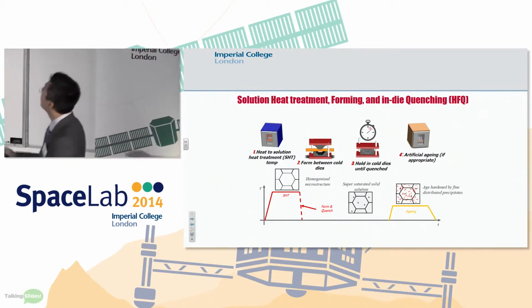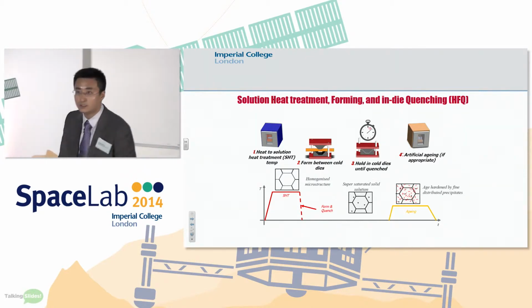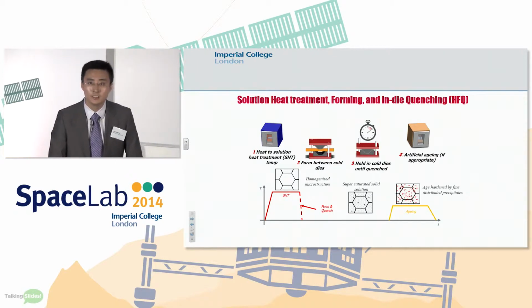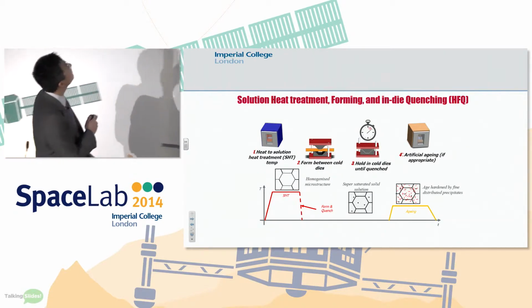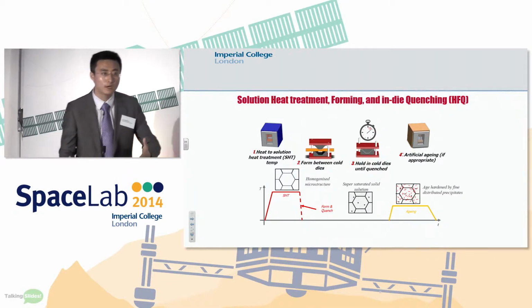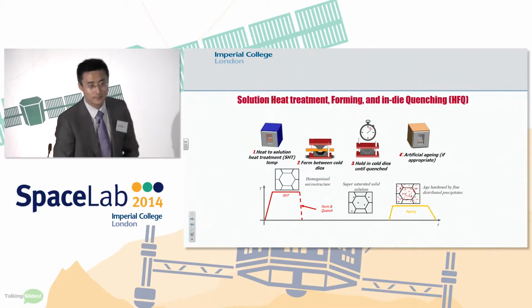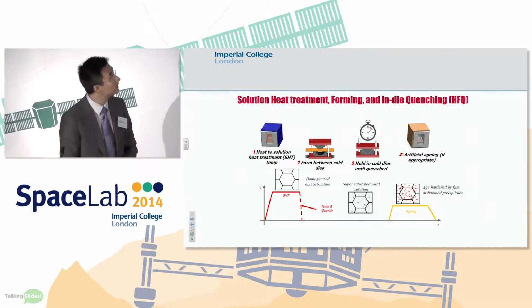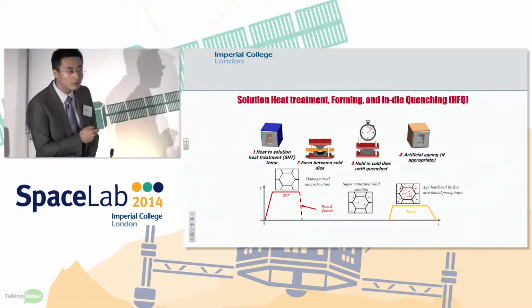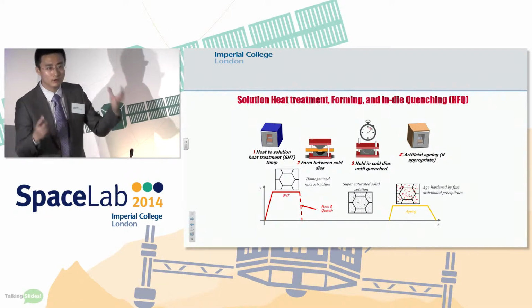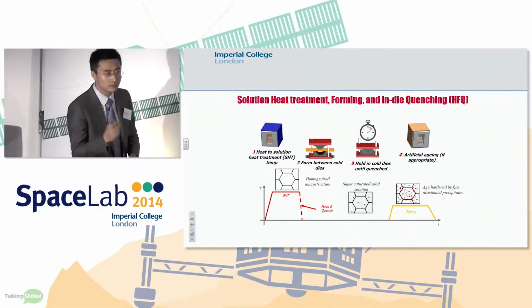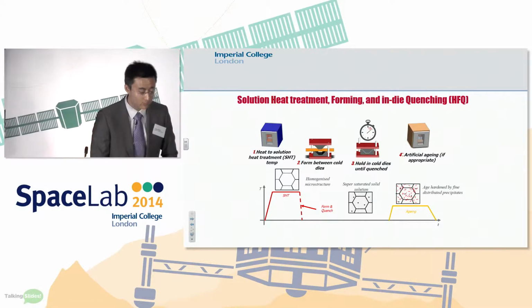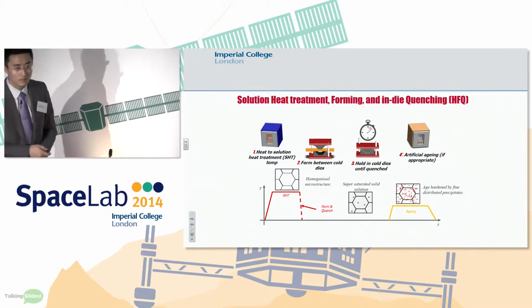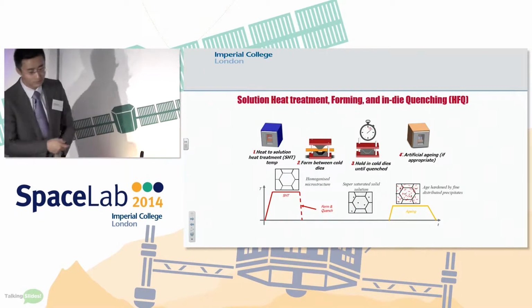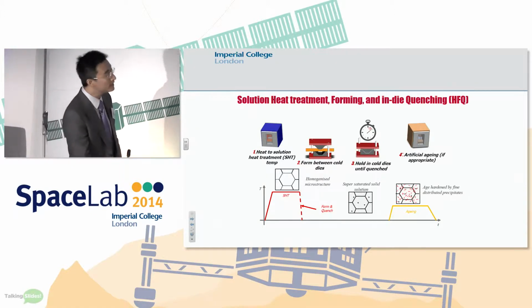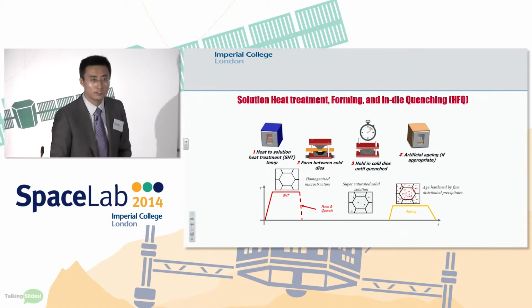At the very beginning, we put an aluminum blank into the furnace to heat up the material to the solution heat treatment temperature. Then we transfer the material quickly from the hot furnace to a cold die. Normally, the cold dies are water cooled. Then we form the components very quickly using the cold die, and the formed component is held within the cold die for a certain period of time, which normally takes a few seconds. Afterwards, we put the formed component into another furnace for artificial aging. By doing this, we can achieve the full strength of the material.